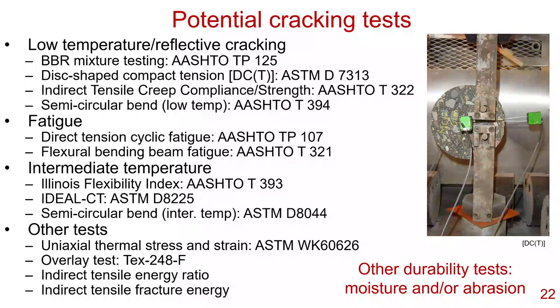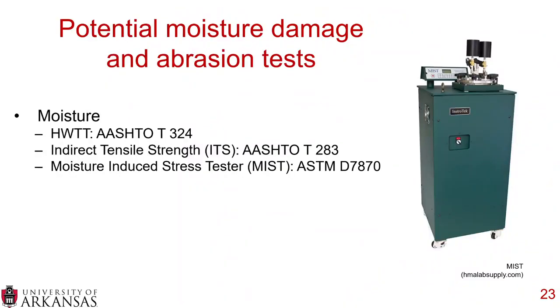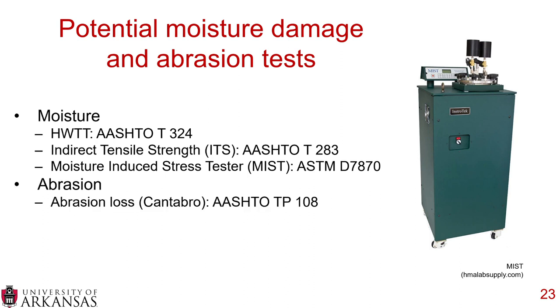Now, remember I had introduced balanced mix design as sort of rutting versus cracking, but some people are starting to look at it as rutting versus durability. And when we think about durability, that includes cracking, moisture, and/or abrasion. So if we look at potential moisture tests, we can look at the Hamburg wheel test, which I personally think is a moisture test. The indirect tensile strength, ITS, that could see the TSR, the tensile strength ratio. And then the moisture-induced stress tester, or MIST. These are all potential moisture damage tests. And then you'll also find that some people are looking at abrasion loss through the Cantabro test.